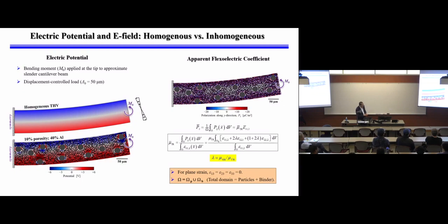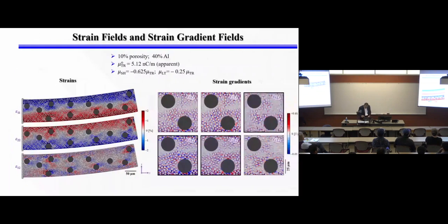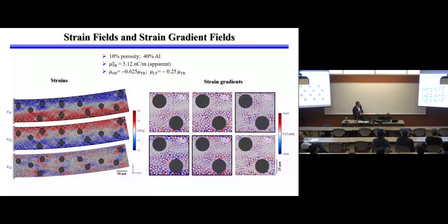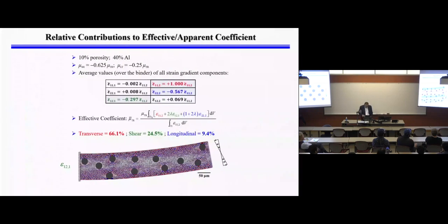But by having the voids, and the metals are not flexoelectric, the voids are empty. They don't have flexoelectricity. Even though you have less volume of the flexoelectric capable material, you actually force the rest of the material to give you more output because of higher stresses, higher strains, and the activation of strain gradients in other ways. So in a nutshell, you have this magnification of this coefficient. I will just show you some quick pictures of, again, for microstructure cases, different strain components. You have three components in two directions. You have six different strain gradients. And all those have to be included and characterized.